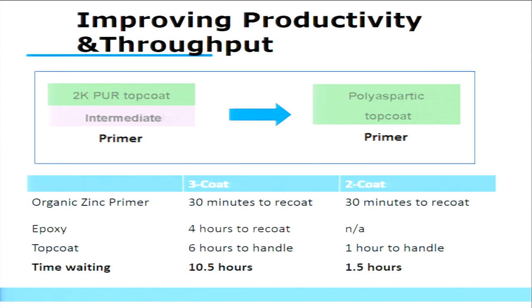It's how long you have to wait between coats before you can go to the next one. And these are just general rules of thumb. I think there's some differences within each paint system, but this is just generally speaking. So 30 minutes to recoat after the primer is installed, 4 hours to recoat after the epoxy, and 6 hours for the top coat. Whereas the polyaspartic, the same 30-minute wait time for the zinc, but after the polyaspartic top coat is applied, you can handle it after an hour. So significant reduction in wait time here for a polyaspartic.